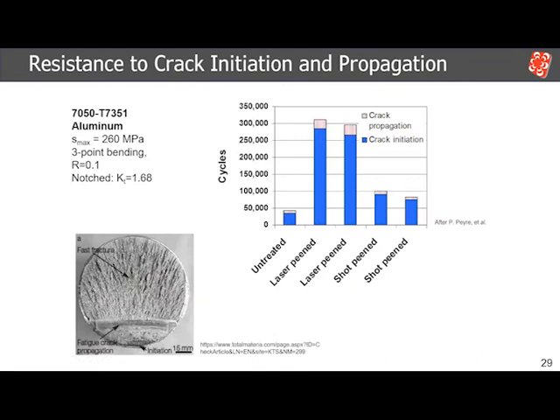This study that was also done on aluminum separated the two aspects of fatigue life. They separated the fatigue crack initiation and the fatigue crack propagation aspects. So the majority of the life, as you can see in this graph, is from the crack initiation. Laser peening, the highest benefit that you get out of it is from the crack initiation.